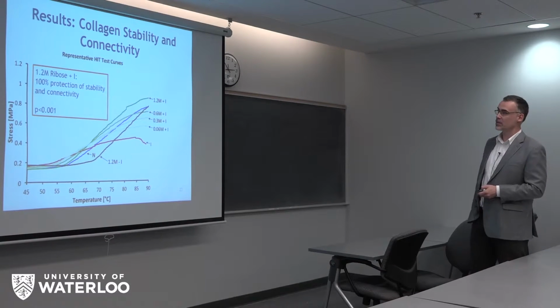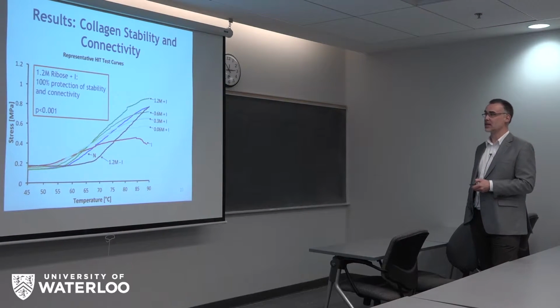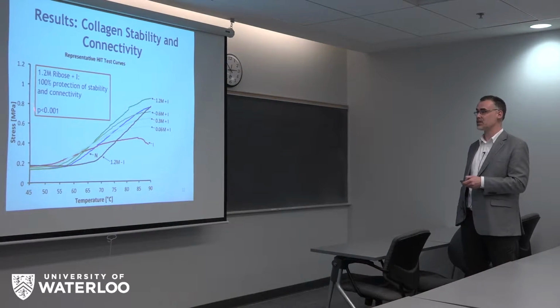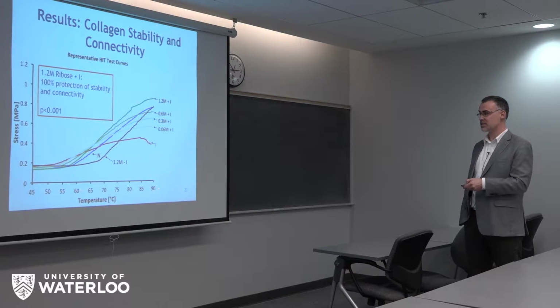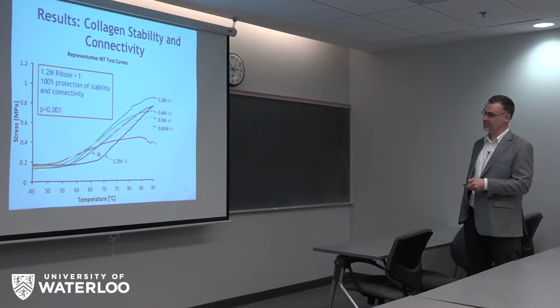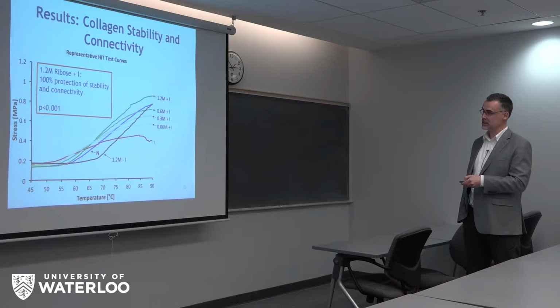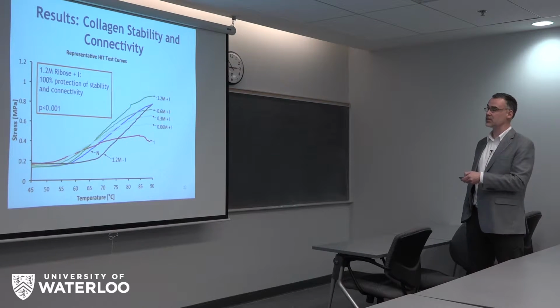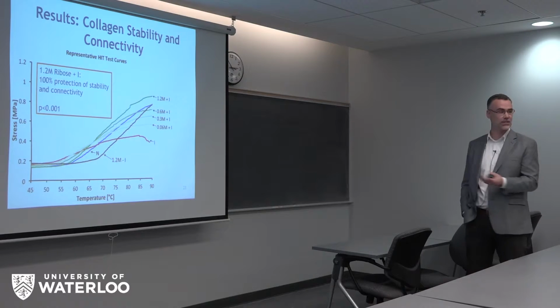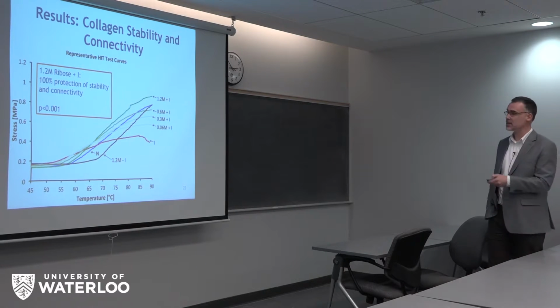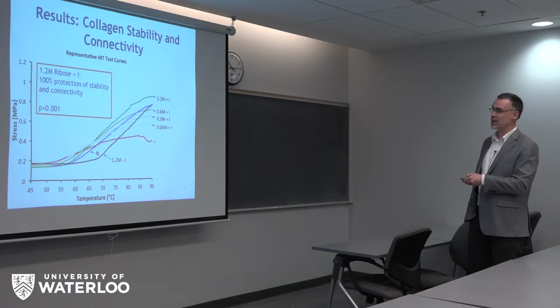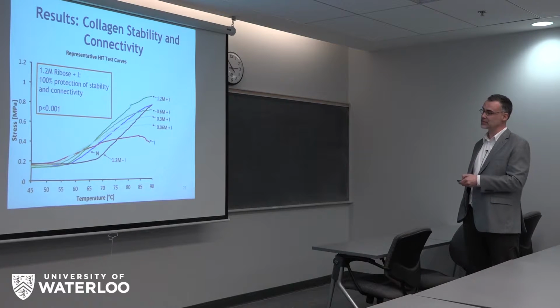And when we evaluated the stability and connectivity of the bone collagen, we have stress versus temperature. Here's blue again, the control. And you see the drastic effect due to irradiation. It starts to melt at a lower temperature. It generates a much lower slope, so that's a lower measure of connectivity, and it actually will rip out of the grips because it's weaker.